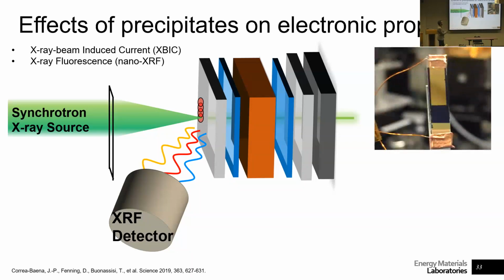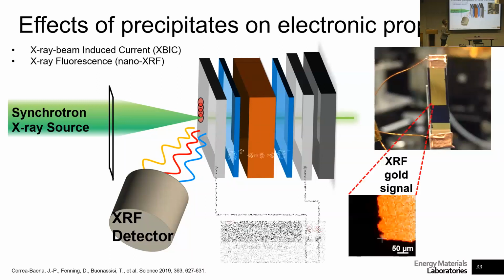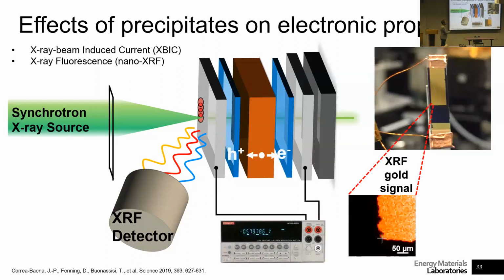Okay, so here is a device that we actually bring to the synchrotron. You can see that little gold strip, that's the device, and here are the contacts. We can connect those contacts to an external source and measure the current that is being induced by those X-rays. So in the first part, the XRF part, that's the chemical part, we can look at, for example, that little corner there that is going to be gold. You can see that patch of gold that looks very straight and nice. Actually, it's not so straight at the nanoscale or the microscale range. But that's the gold signal, right? So that's that little corner there.